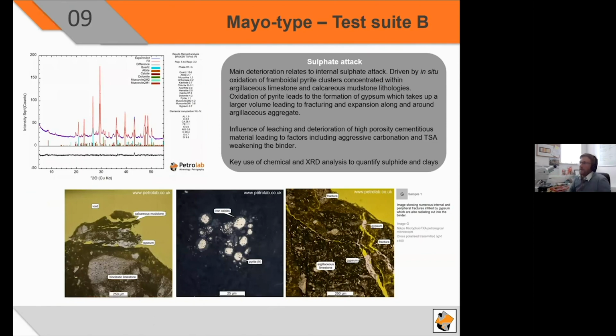So, if we split down to look at the pyrite route, County Mayo type, the main type of deterioration noted in these samples is a form of internal sulfate attack, driven by oxidation of framboidal pyrite clusters concentrated within the argillaceous limestone and calcareous mudstone lithologies. Oxidation of pyrite leads to the formation of gypsum in situ, which takes up a larger volume relating to fracturing and expands along the edge of aggregate particles and internally with aggregate particles to force the binder apart.